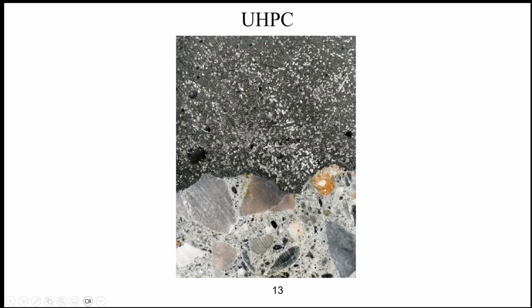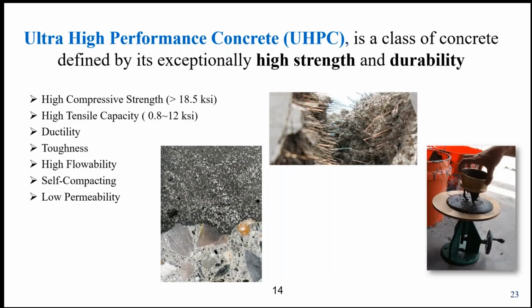The reason for that is that ultra high performance concrete doesn't have that much water. The water-cementitious ratios are on the order of 0.2, 0.18. So if the surface of the conventional concrete that you're going to spray over is not adequately moist, at least 24 hours before the spray, then it's going to absorb all that little water that's in the UHPC, and it's going to cause a crack.